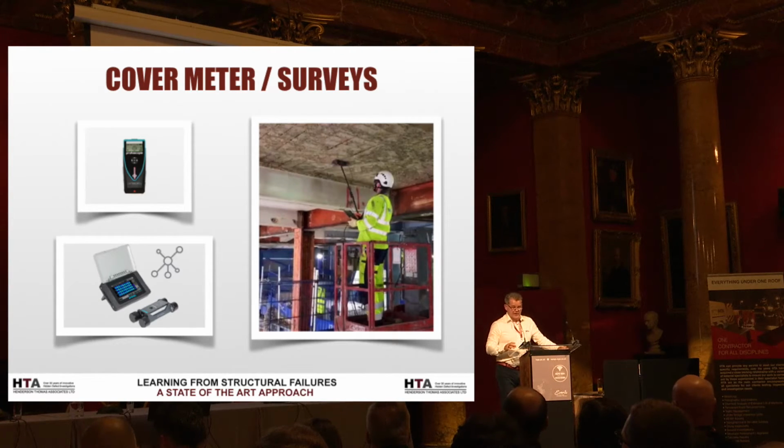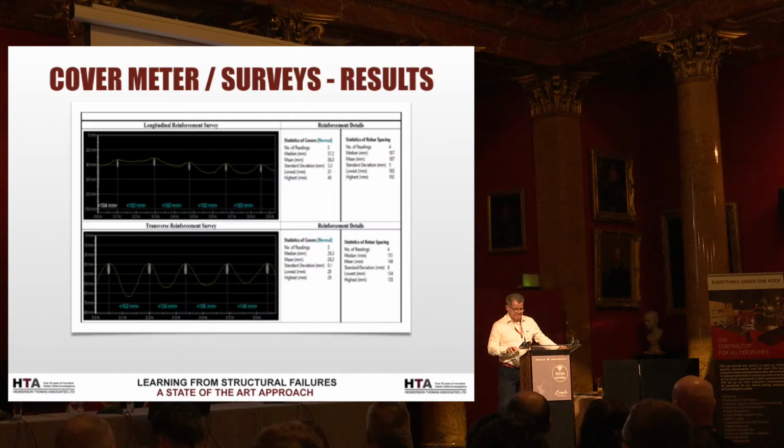Please be very aware, if you're doing an assessment of a structure, one of the companies who produce a certain cover meter that say you don't have to break out is Hilti. And they're the bane of my life because I've gone along and had to go in and guys are going, no, you just tell me what the cover meter says. Hilti, when you push them on it, slightly economical with the truth, it's plus or minus 1 bar size. So any of the structural engineers here, if I tell you it's a half inch bar, could be 16, could be 9 mil. It's going to have a massive implication if your structure is going to stand up to an assessment.